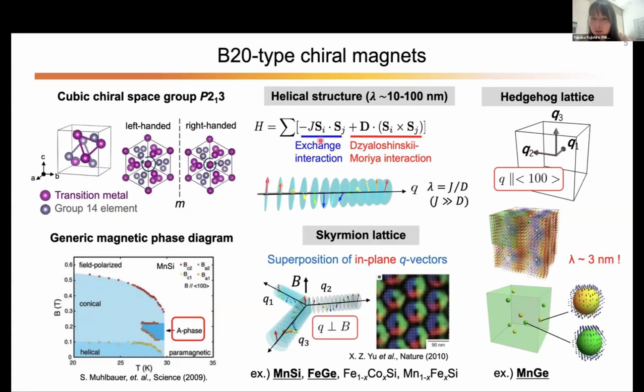As a result, when there's a competition between ferromagnetic exchange interaction and this Dzyaloshinskii-Moriya interaction, the magnetic ground state in this family of compounds is typically a long-range helical spin structure, where the magnetic period is determined by the ratio of the exchange and the Dzyaloshinskii-Moriya interaction. This is the typical generic magnetic phase diagram of these compounds. As I said, the magnetic ground state is a long-range helical state, while a very small pocket near the transition temperature has a skyrmion lattice state, which can be described as the superposition of three in-plane helix states.